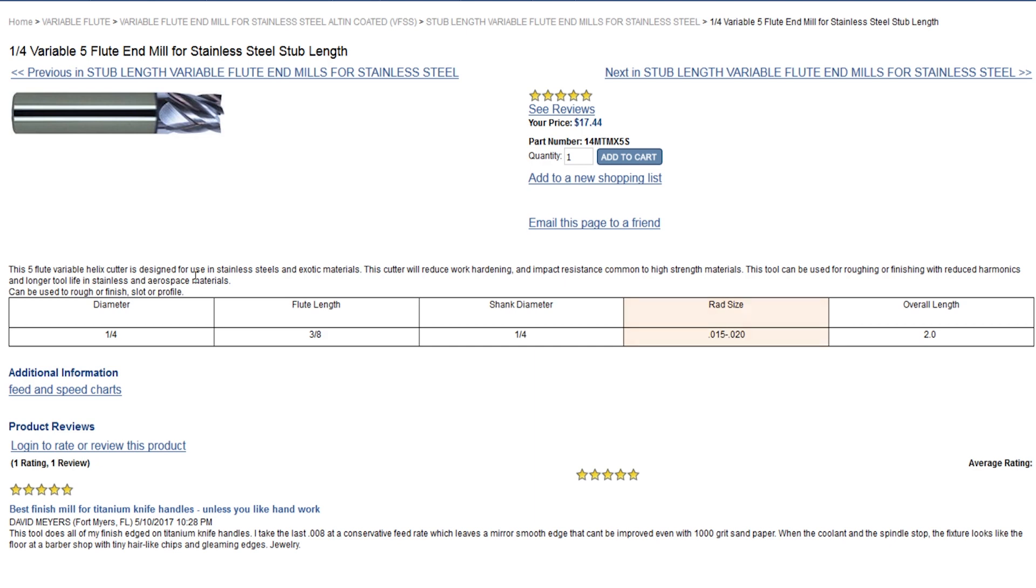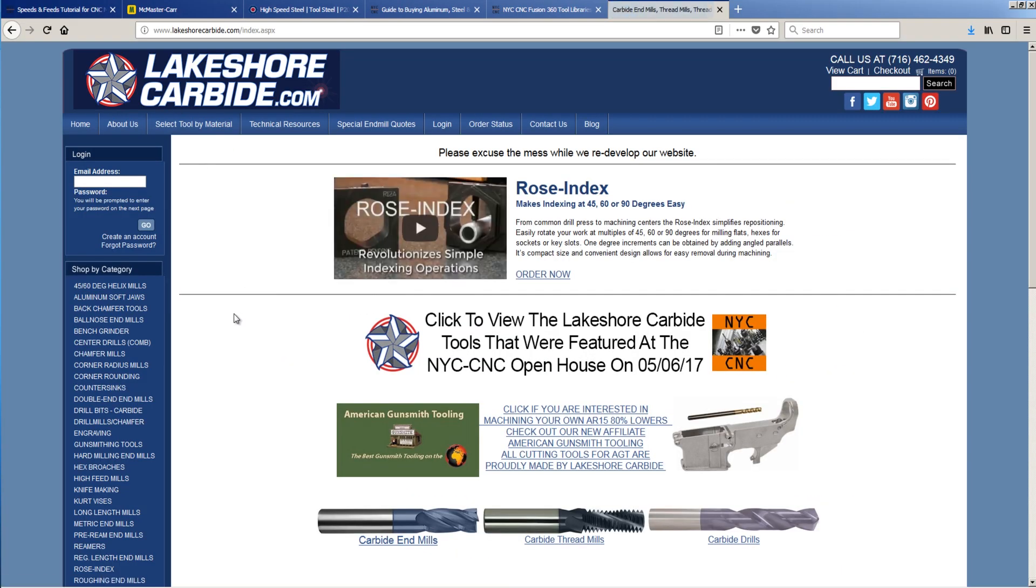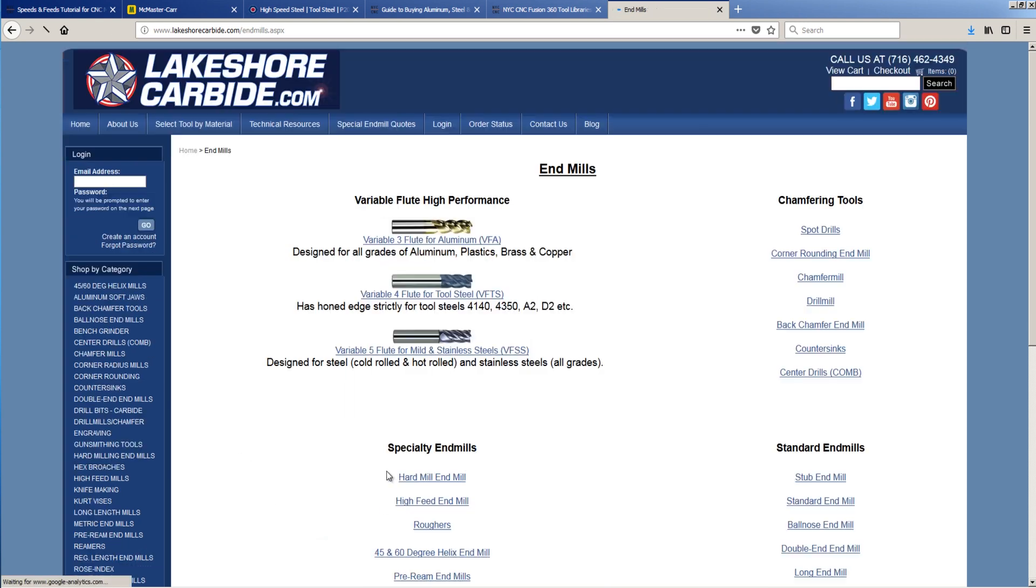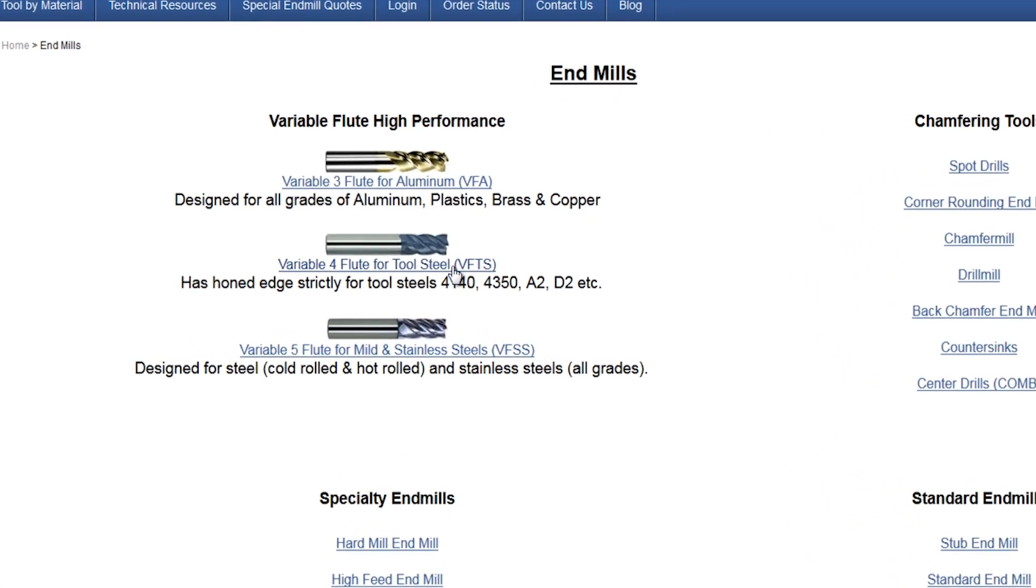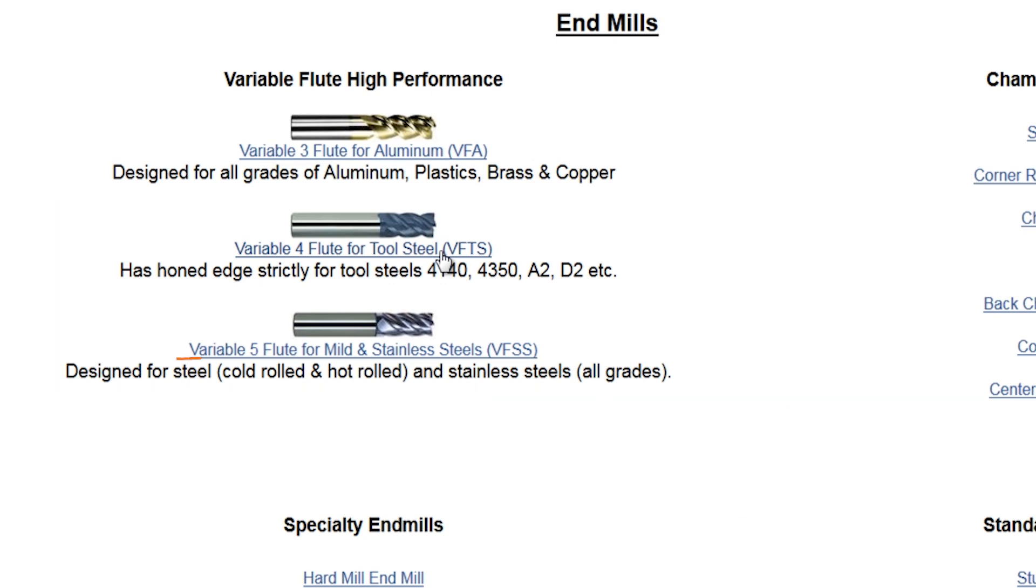It's got a small corner radius, which I really like. That helps increase the strength of the corner of that tool by getting rid of that sharp point. And we'll run this tool between two and three thousandths of an inch feed per tooth, which means you're really cooking. In this case though, because we're using a tool steel, if we click on the carbide end mills, variable four flute for tool steels. And so there's a number of difference between these two tool geometries, but the one that matters the most here is how sharp the edge is. The five flute tool happens to have a sharper edge that helps you shear in either softer materials or gummy materials like stainless. The four flute here for tool steels, or 4140, has a slightly more honed edge, which means it isn't quite as sharp, but it's going to hold up a lot longer.